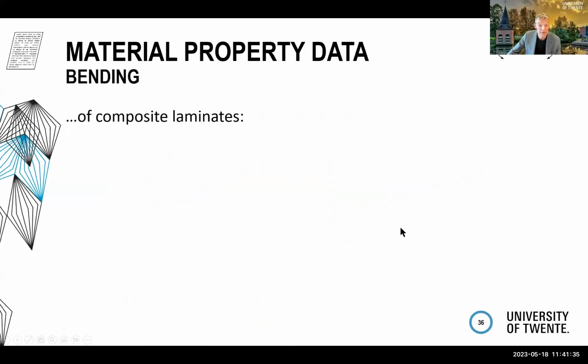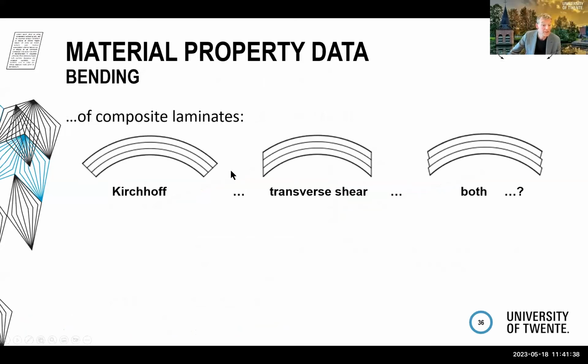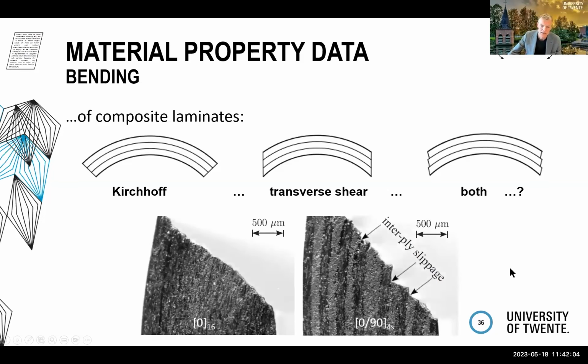Bending, the third mechanism I would like to discuss briefly with you. Well, this is the classical Kirchhoff bending, normal cross sections remaining normal to the center line. Obviously, these composite laminates are subject to transverse shear during bending as well, and obviously there may also be slip between the plies. So, what to do with this? Again, this is what happens in a unidirectional material. Again, the same L shapes as shown before. So significant transverse shear and repeating this interply slippage for 0/90 L-shaped specimens. So what to do with that?